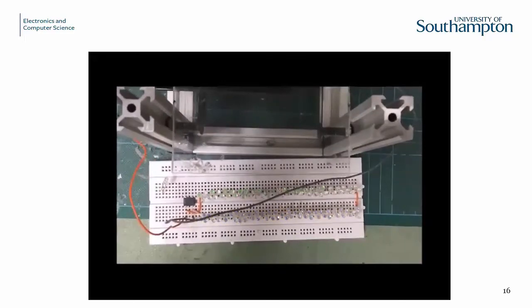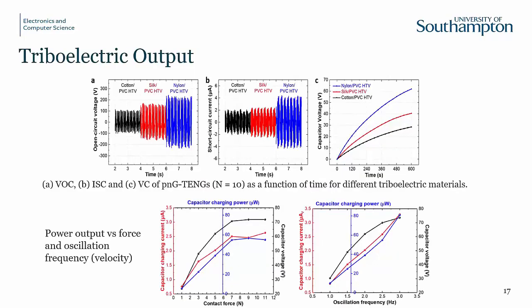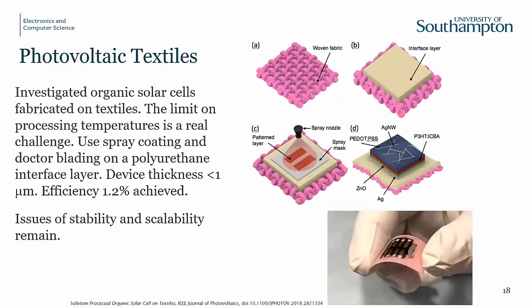So, from an energy harvesting point of view, we want to quantify the energy more accurately and look at different textiles, for example. So we've looked at cotton, silk, nylon is the best combined with the PVC, and we're getting 80 microwatts typically out of that sort of application with that sort of stroke range or amplitude range. It does depend upon the velocity, not so much on the force, so the force isn't so important, it kind of levels out. But a very, very promising approach for energy harvesting with textiles, because there are many applications where textiles are typically sliding against each other.